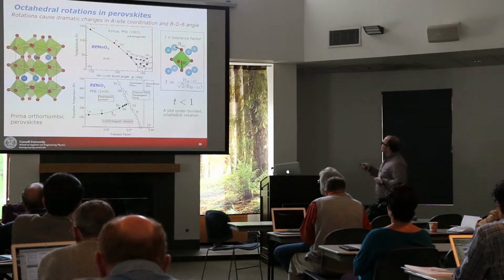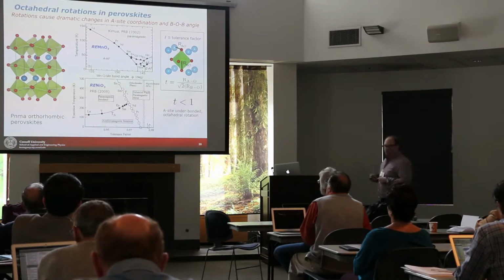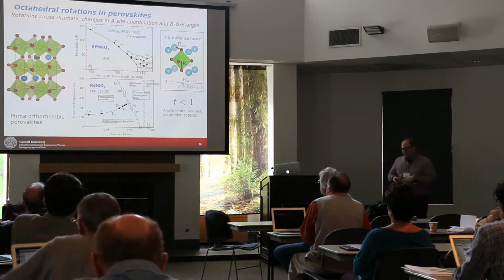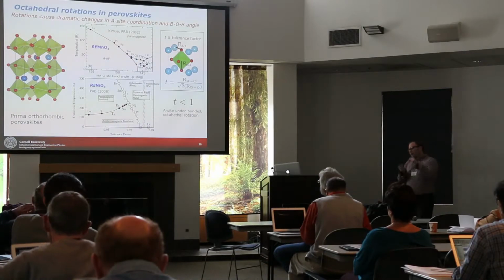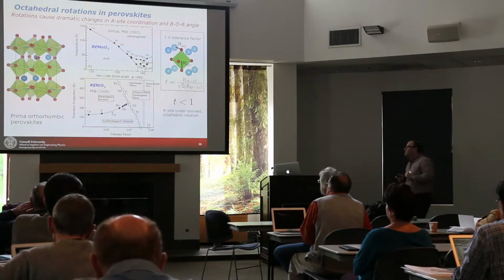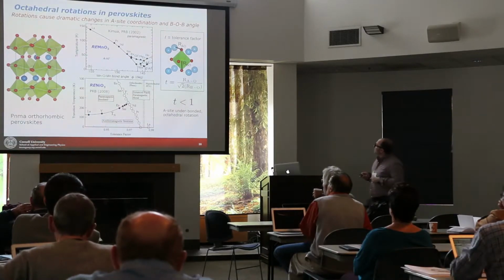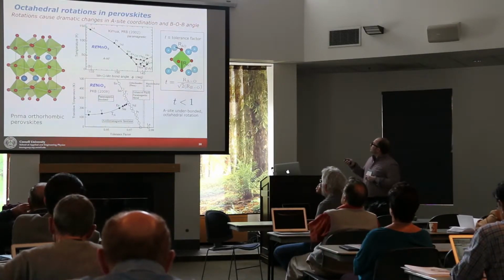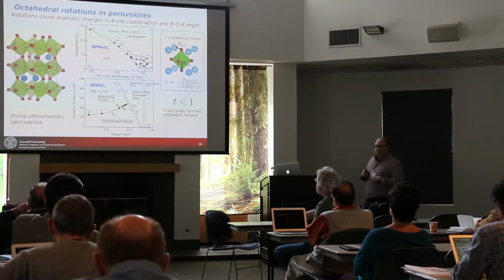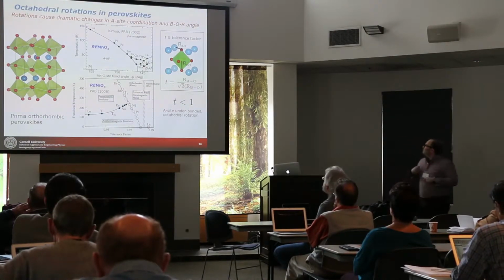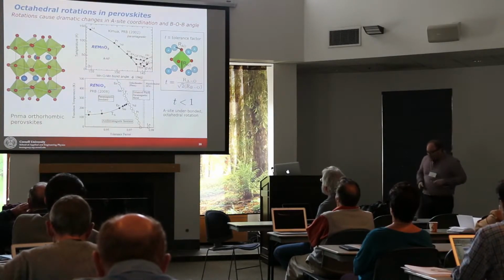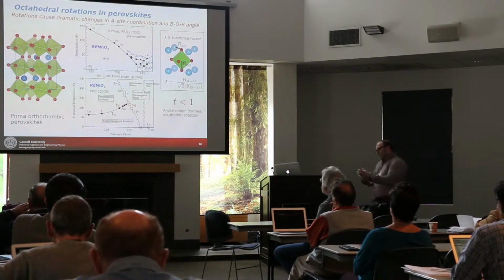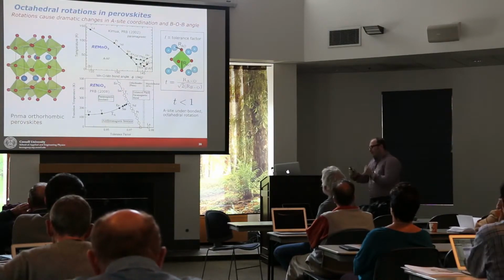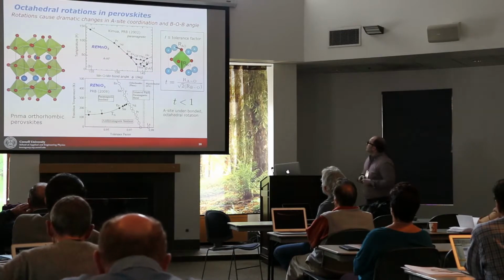What I'm showing you down here is plotted versus tolerance factor. Just know that way of plotting. The tolerance factor is a geometric descriptor. Imagine that we have this cubic perovskite structure. Just imagine you pack these as hard spheres. The ideal packing of hard spheres would lead to a tolerance factor of 1, but if the A site was much smaller, this tolerance factor would be less than 1. Chemically, that means that the A site's bonds are very unsatisfied. The crystal structure will want to distort in order to accommodate the chemistry of its A site bonding environments. And that's what we're doing here.